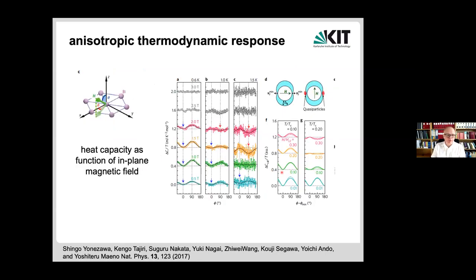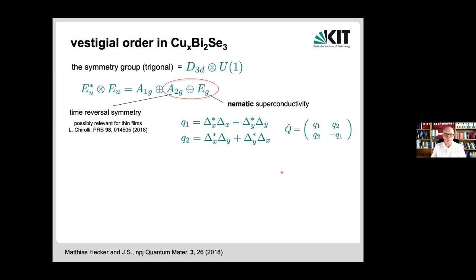Other experiments have seen similar anisotropies. I'm just showing you one example. Heat capacity as a function of the angle, which is another thermodynamic measurement, and you also see this twofold anisotropy in the system. There's also anisotropies of the upper critical field, which is an independent and quite interesting story. Again, you find a twofold rotational symmetry breaking. Okay, we know what to do.